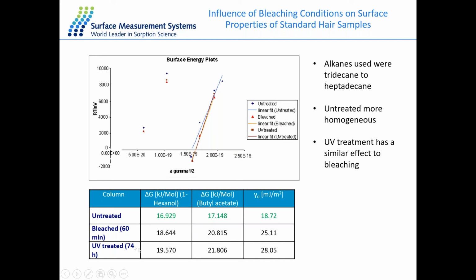What's also interesting is that we have different types of treatments, bleached and UV. However, what we're seeing is that the interactions and the surface energies are actually quite similar. So they actually have quite similar effects to each other.